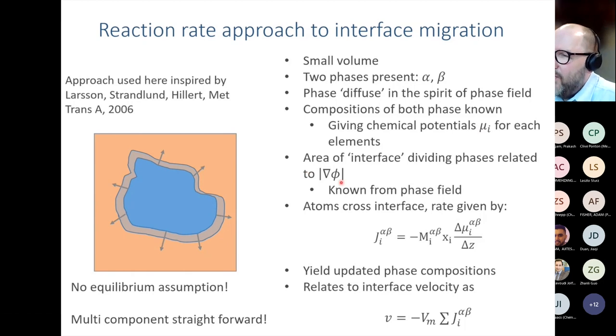And you can also determine the area of the interface that separates the two phases. And it can be shown that this relates to the magnitude of the gradient of the order parameter. And we know this from phase field, that's given from our phase field equation. If we combine all of that, we can actually calculate the rate at which atoms are crossing the interface from, let's say, the alpha phase onto the beta phase. So that means the blue phase will be growing and the orange phase will be shrinking.